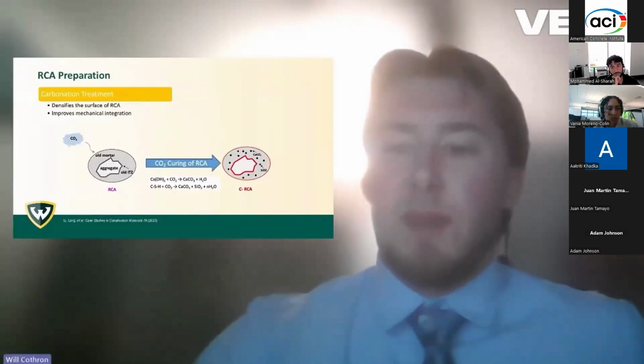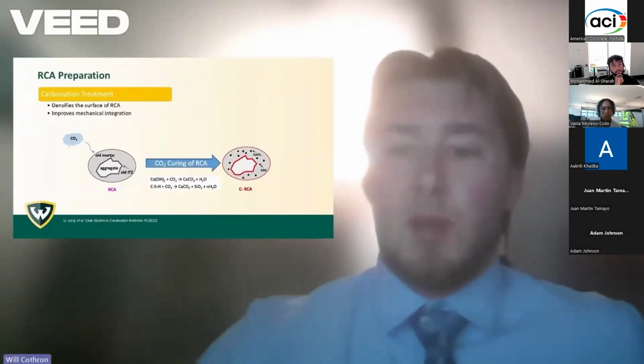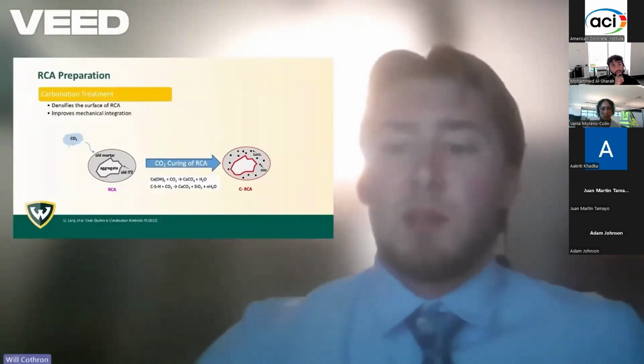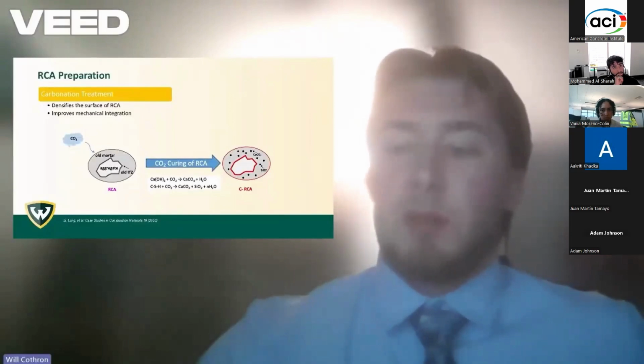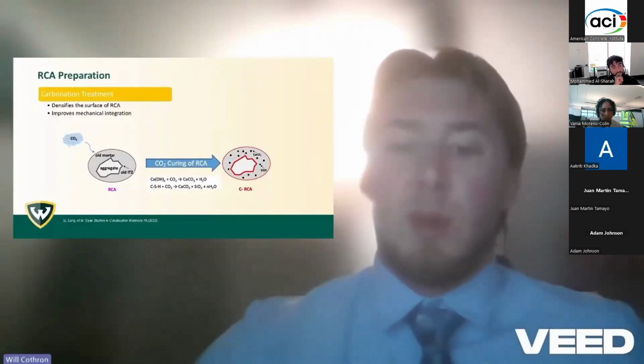One way to address the disadvantages of recycled concrete aggregates is through a method called carbonation treatment. This treatment involves curing the RCA with carbon dioxide. When CO2 interacts with the old mortar on the RCA surface, it creates a denser, stronger outer layer. This is shown in the illustration on the right side of the slide, where carbonation changes the surface chemistry by producing calcium carbonate. These chemical reactions help fill pores and strengthen the old interfacial transition zone, making the RCA particles denser and improving their mechanical properties.